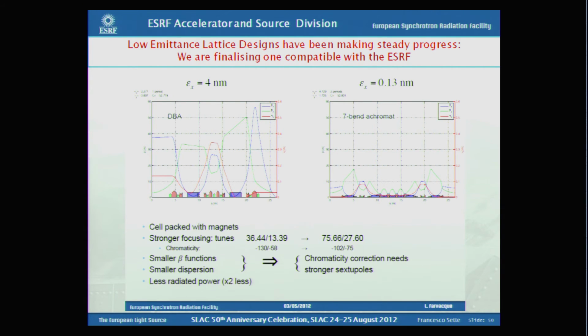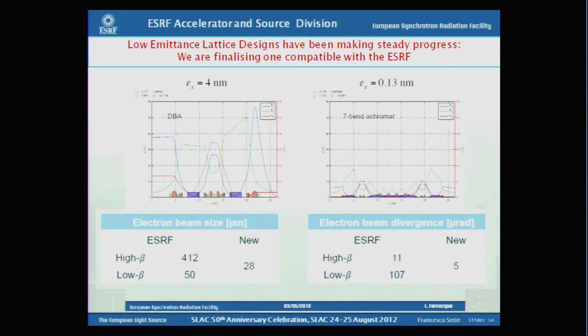And plans are to go to a new machine with an upgraded and reduced horizontal emittance, that is reduced by almost a factor of 30. This simulation here shows 0.13 nanometers, and you go from a double bend achromat to a 7-bend achromat. These are the electron beam size characteristics. So you see today we have 2 kinds of lattice which are interpenetrating, high beta and low beta. In the new there will be only 1 lattice.